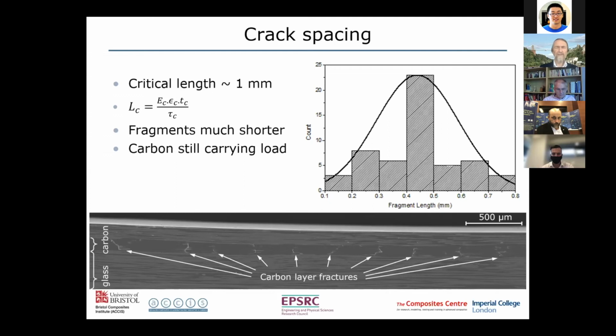So if you put the numbers into that equation, you work out that the critical length should be about 1 millimetre. But actually, these fragments have a much closer spacing, with an average of about 0.4 to 0.5 and a distribution of those. So the fragments are much shorter than the critical length. And what that tells us is that the plies are still carrying load. After they fragment, they're still carrying load.